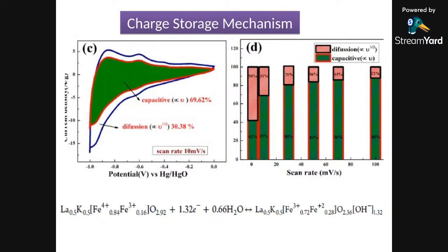Then we studied the charge storage mechanism, because most perovskite people talk about oxygen intercalative storage. However, it is not at all possible to have oxygen intercalation into the material if you don't have very high oxygen vacancies. There cannot be an oxygen-excess perovskite. Oxygen-excess perovskite is a myth.